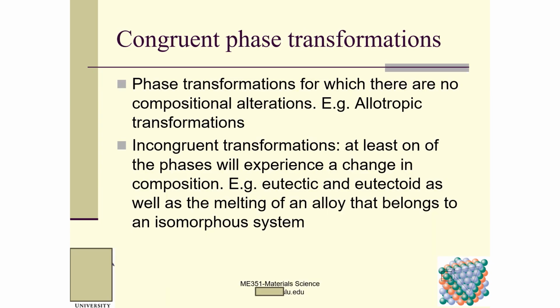So congruent phase transformation is a phase transformation for which there are no composition alterations. For example, allotropic transformation. This is from alpha to beta. These alpha and beta are from the same material. Okay, incongruent transformation, at least one of the phases will experience a change in composition. For example, eutectic and eutectoid, as well as melting of an alloy that belongs to an isomorphous system. So this is a congruent phase transformation.